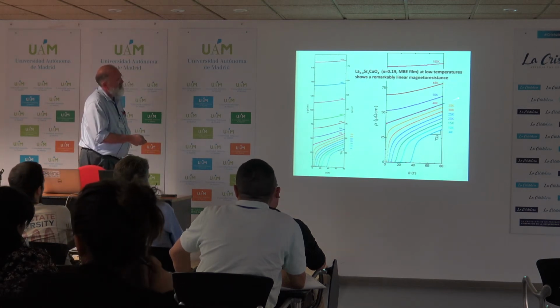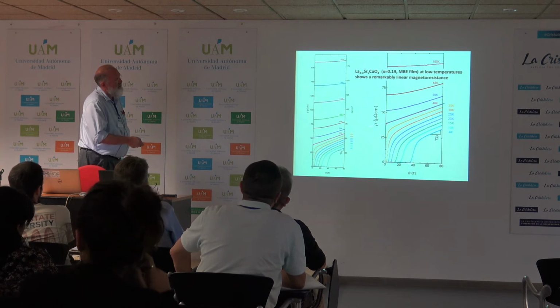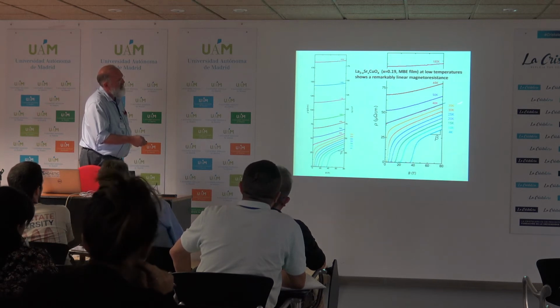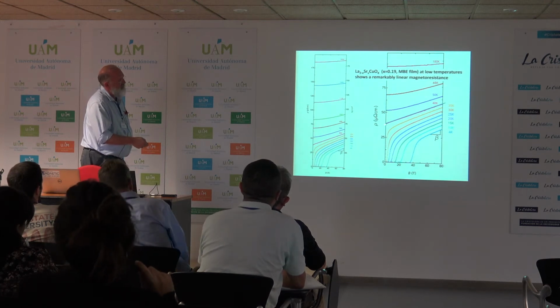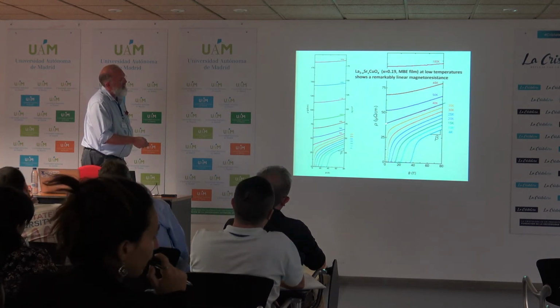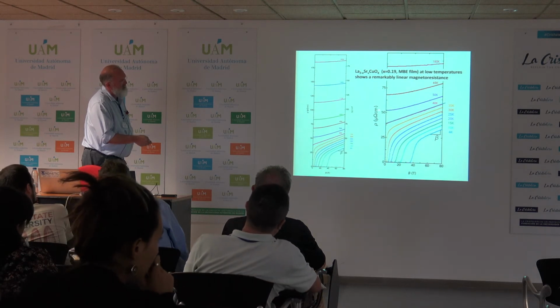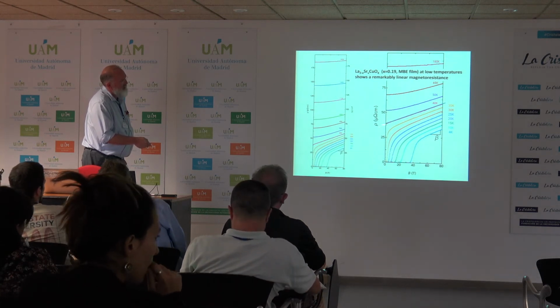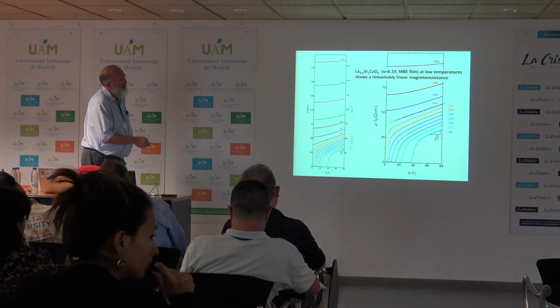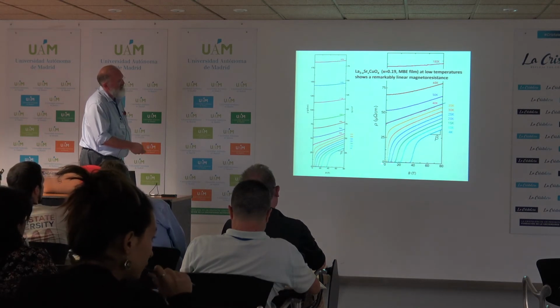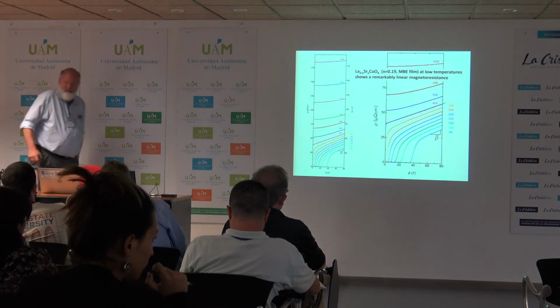is really quite clear in this system, is that you get dead linear almost down to zero field right near TC in zero field. There's a little bit of superconducting fluctuation there, and we do know that by symmetry you've got to have some B squared component, but it really does seem to shrink to almost nothing, and you get this linear behavior, in this case from just a few Tesla all the way up to 80 Tesla.